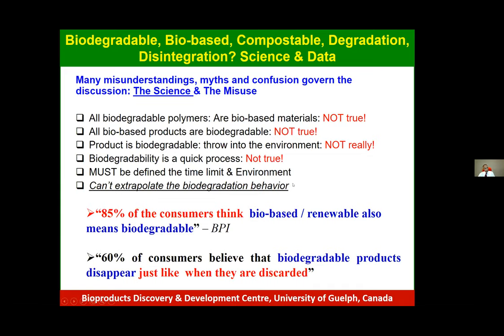You cannot extrapolate the biodegradation behavior. People make a design of experiment in engineering or science, and suppose somebody does a biodegradation test in the laboratory, and my product in the experiment degraded 10% in 7 days. So 100% will be 70 days. You cannot stop the experiment and assume that. You cannot extrapolate the biodegradation. You have to run the experiment till the end of the required time period. 85% of consumers think bio-based or renewable means biodegradable. That's not true. 60% of consumers believe that a biodegradable product disappears right when discarded. That is not true. I explained those.